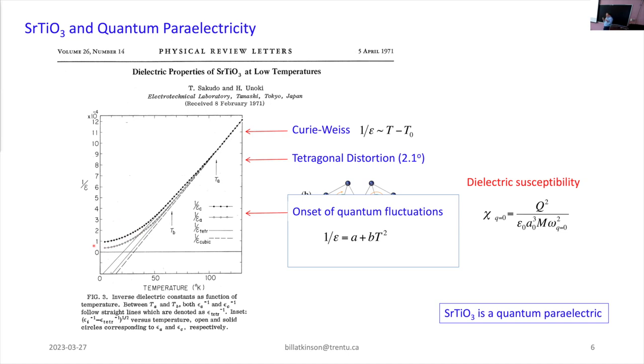And the thing that is really amazing to me, it still amazes me, is that this is due to the quantum fluctuations of the phonon mode. So the phonon mode is a quantum object, and it's the zero point motion of that mode, so the zero point motion of the titanium atom, effectively, that keeps it from settling down in an off-center position.